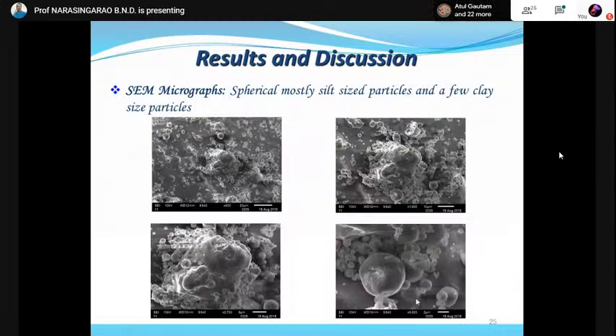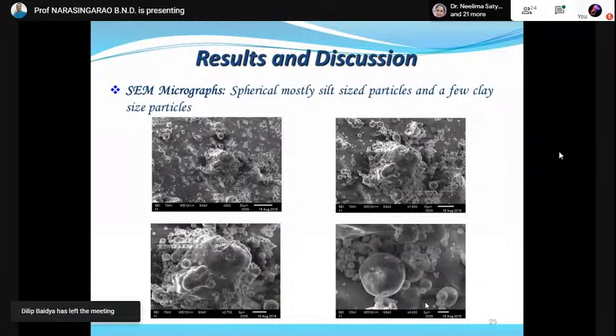And these are the scanning electron micrographs at different resolution. This is 20 microns, this is 10, this is 5, and this is 2 microns. So these micrographs reveal that most of the particles are spherical in shape.